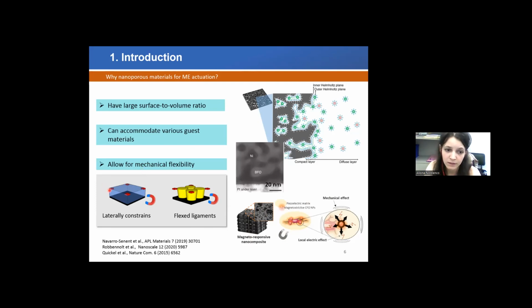So, for example, in continuous films grown on a rigid substrate, there is a so-called clamping effect. So the film is strongly bonded to the rigid support, and even when the magnetic field is applied, there is no way for the material to deform. However, if the material is made porous, then the bottom of the ligaments will still be clamped to the substrate, but the top side of the pillars, or of the ligaments, may still be expanding or contracting due to the absence of lateral constraints.